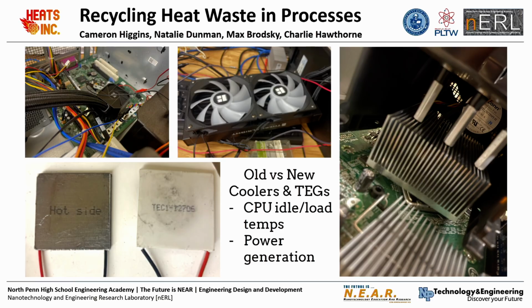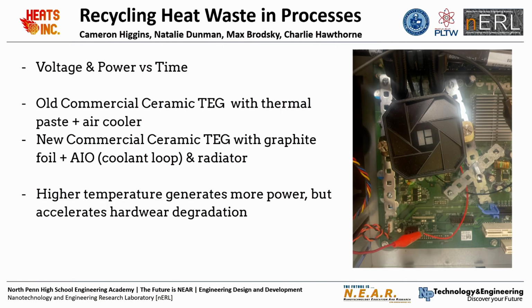We compared new and old commercial TEGs, and we also used different ways of cooling them and measured the power generation statistics. We found that the better it could cool itself, the more energy it could produce. Because while we found that a higher temperature difference does generate more power, what is also important is making sure that it stays cool and doesn't thermally bottleneck.